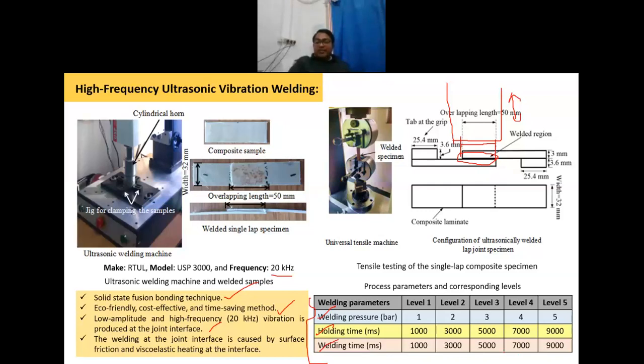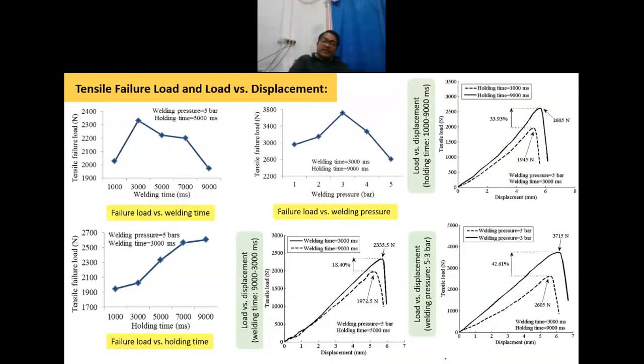And welding time, that means the time you are giving for the vibration of the ultrasonic horn, this cylindrical horn. Again, it should not be very high and it should not be very low, because if the horn vibrates for more time, there will be more heating at the joint interface. That means there will be excessive heating and excessive melting of the polymer. But if welding time is low, there may not be an adequate amount of heat generation, and due to that there may not be adequate melting of the polymer. So very high and very low levels of welding time will detrimentally affect the joint strength. All these parameters we have investigated, and we have done the tensile testing of the joint specimen.